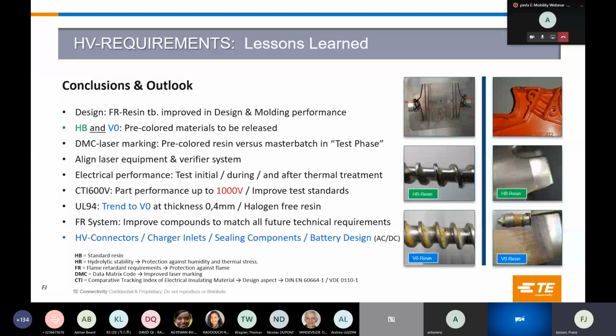So therefore 1000 volt is one of the topics, but also the material performance initially under test validation conditions in the lab, but also after thermal treatment. So we expect the dielectric strength to be measured after thermal treatment. We expect CTI values to be measured after thermal treatment, and also resistivity. Because if you compare polyamide versus polyester, then we see some differences there. So we need to conclude which is the better material candidate based on the specific requirement.